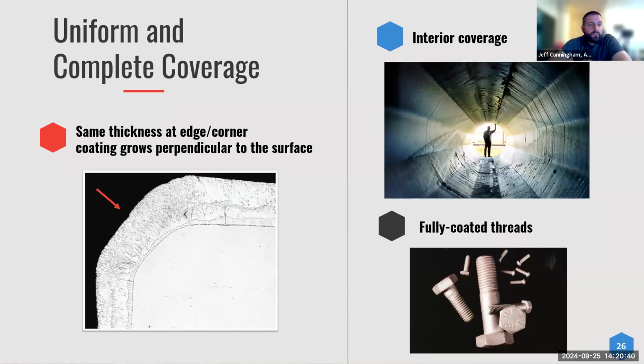All right, uniform and complete coverage as well. I mentioned the interior coverage, and everything gets coated because it's a full immersion process, but you also get the same thicknesses at the edges and corners, because the coating grows perpendicular to the surface. So it's a chemical reaction, or it's a metallurgical reaction. So it's actually growing at every surface at the same amount. So you don't have thicker parts on flat pieces, or on the edges. You might with paint or another coating system, it might be less. So you get fully complete coverage.